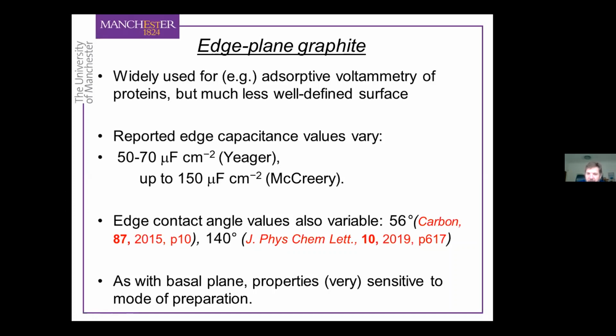interface. Now, part of this is because the edge plane is much harder to prepare in a uniform way. So it's harder to get an edge plane that's got a defined surface area with very reproducible surface chemistry, because it will depend much more on the sample itself and on the history of the sample. So that's part of the reason for these discrepancies. But again, this is always to emphasize that there's a lot more work that needs to be done to understand the properties of both the basal plane and edge plane of graphitic materials.